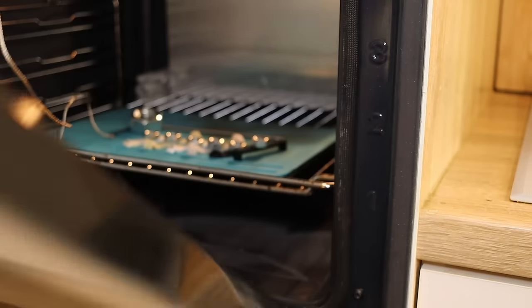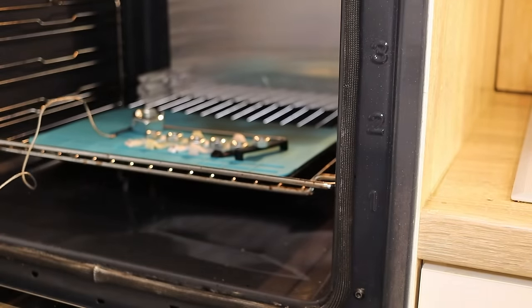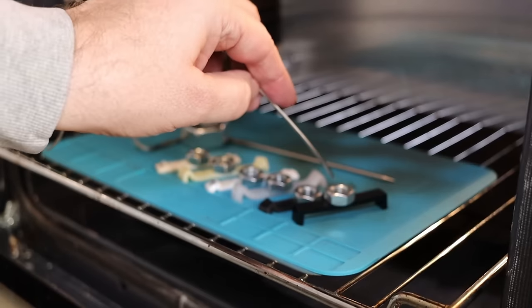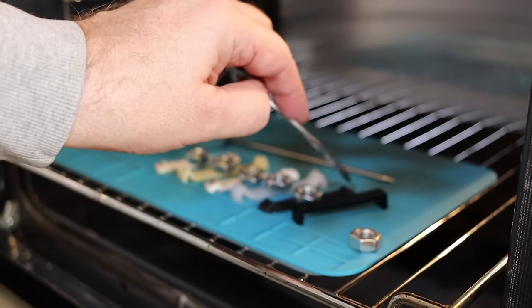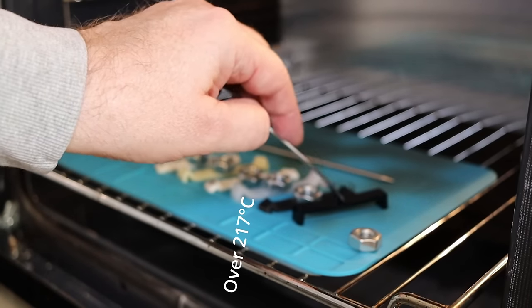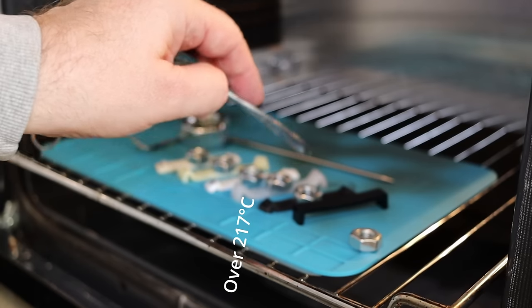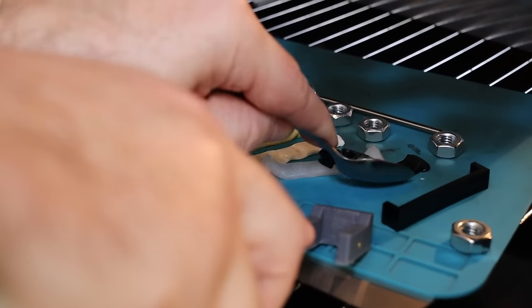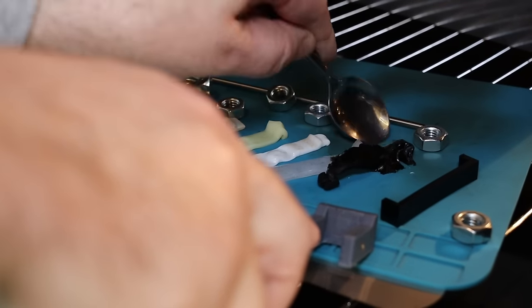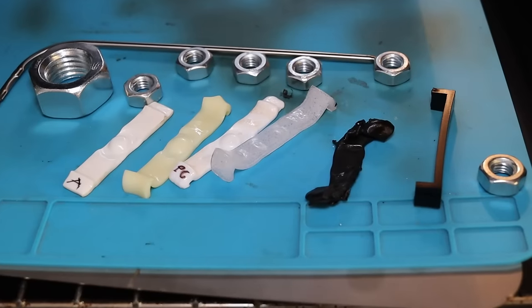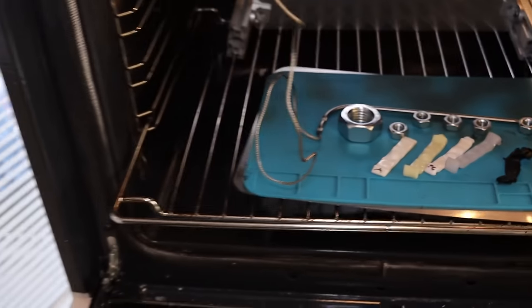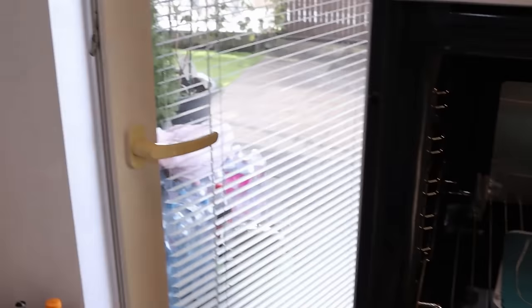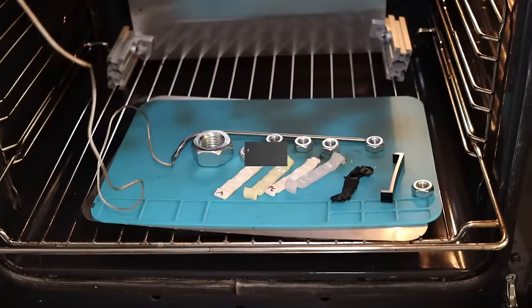And still no deformation on CNC machined nylon. And I'm curious about this nylon. It is still completely hard, 217 degrees Celsius. Interesting, only 3D printed nylon stuck to this silicone pad. I think the winner is quite obvious. And now I have to ventilate the oven and the room, and then summarize the results.